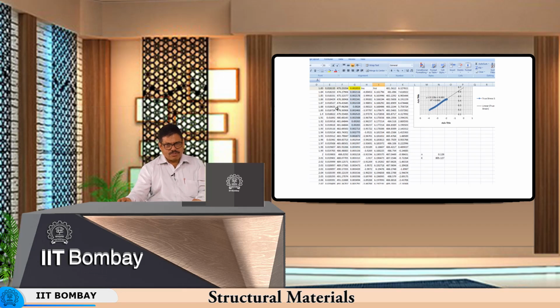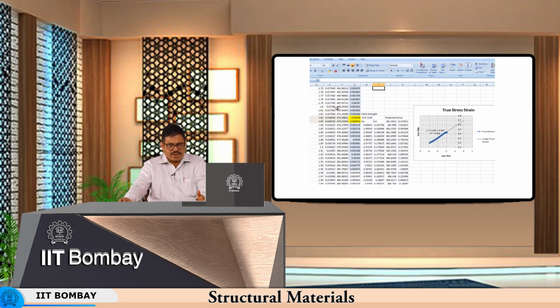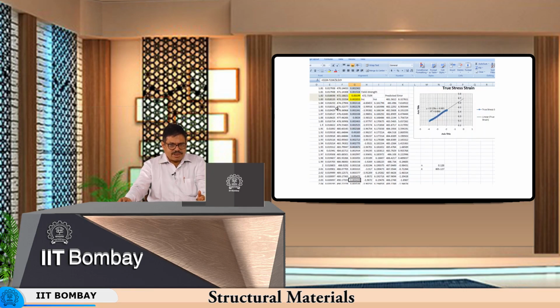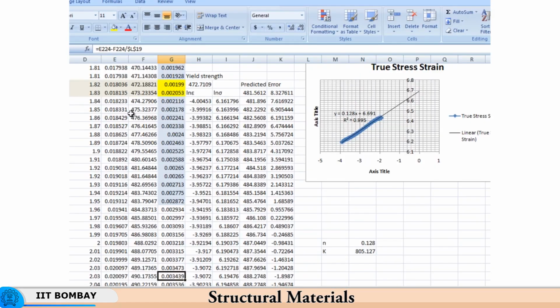I mean, we have assumed that up to 0.2% proof stress. So, the plastic strain, here you see that it is a very small plastic strain, and the plastic strains therefore are comparable with the elastic strains which we had taken here. So, 0.002, 0.003. So, for example, here the plastic strain is comparable with the elastic strain. So, we had put our yield point at 0.002, this is 0.003.